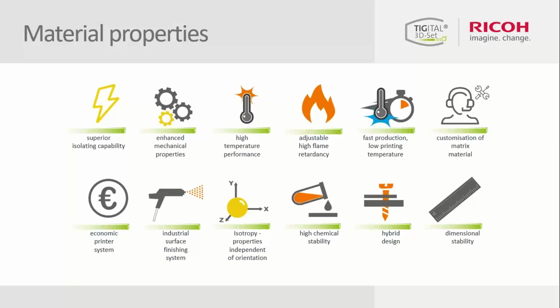And based on this 3D cross-linking during the printing process, we have the advantage that you can achieve isotropic properties in X, Y, Z direction. The other important point is that it doesn't matter where you print the part, on the left side of the printer bed, on the right side, back or forward. Because of the low printing temperatures which we are using, you don't have the problem with thermal control in the printer like when using PA6 or PA12 materials, which are commonly used. And thermoset materials have an excellent chemical stability, which we already explained.